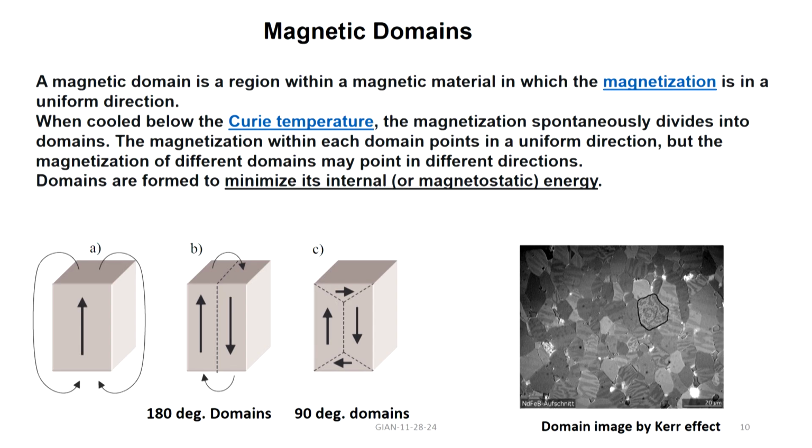So, there will be a small change in the polarization angle, and when you use the detection, the different grains will show up as a change in the contrast. So, these are grains of different orientation on the surface of some sample, I do not know what sample this is. That is how you do the grain imaging using the magnetooptic Kerr effect.